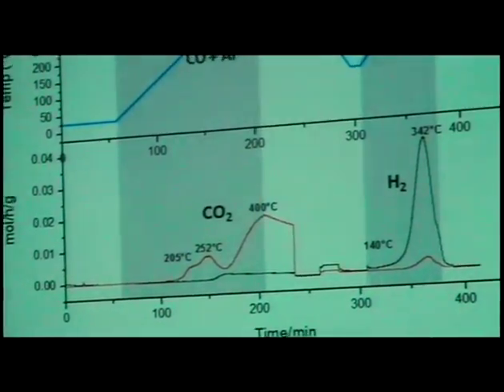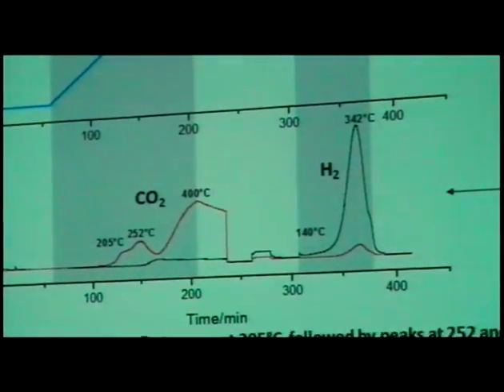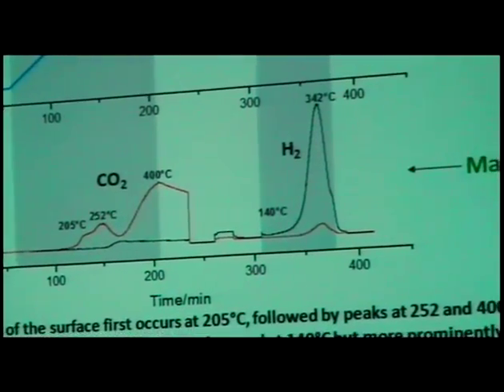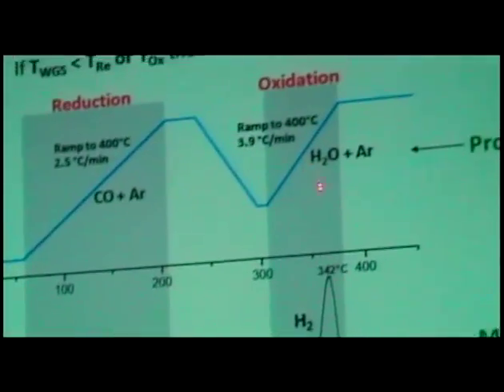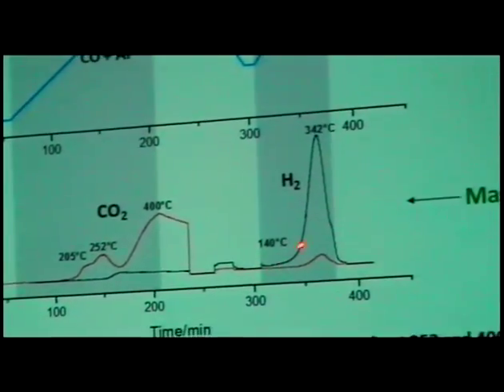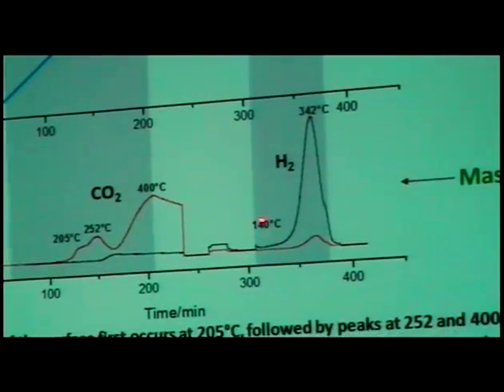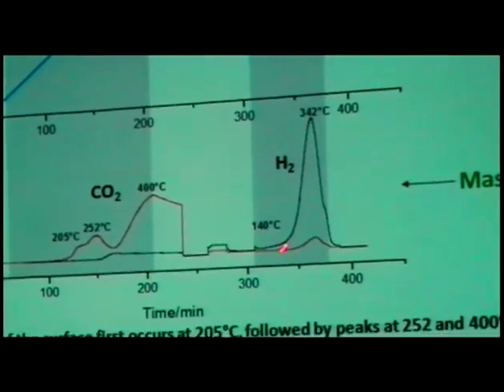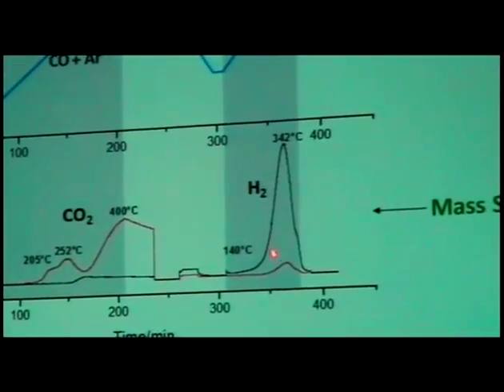Okay? Then, since the catalyst now has been reduced by CO, we hit it with water to reoxidize it and to make hydrogen. And here again, you can see hydrogen being produced, starting at 140 degrees and going up to 342.